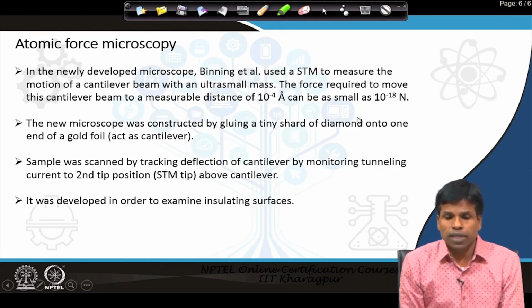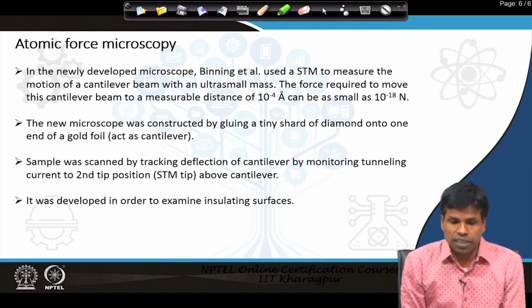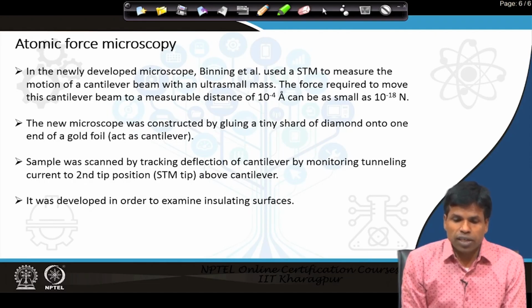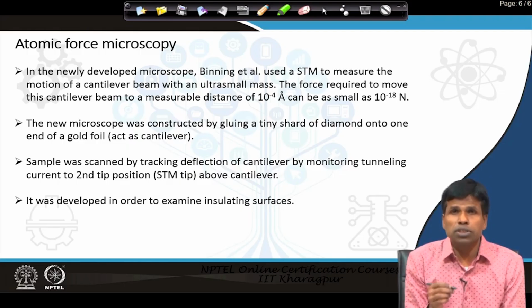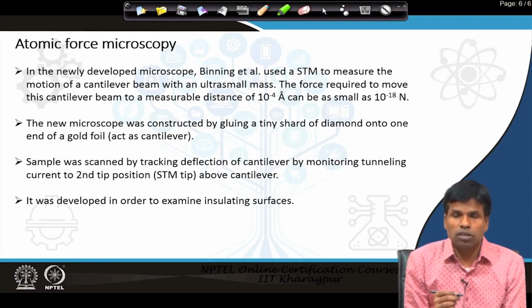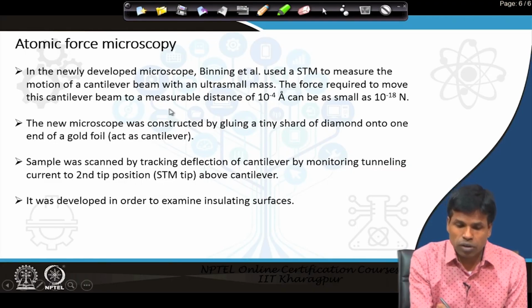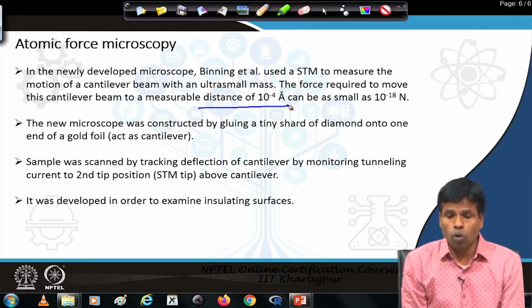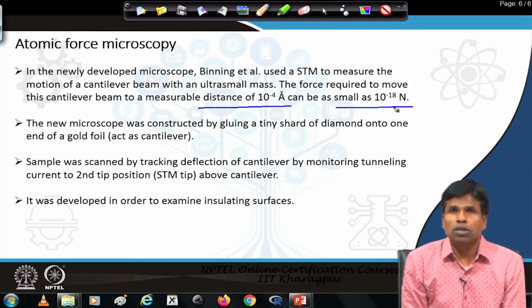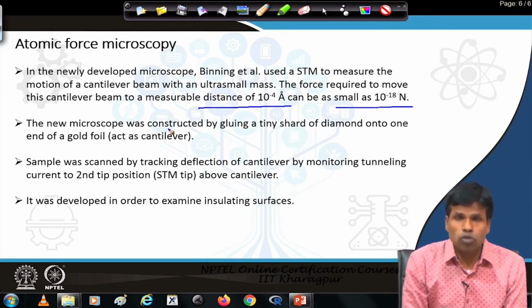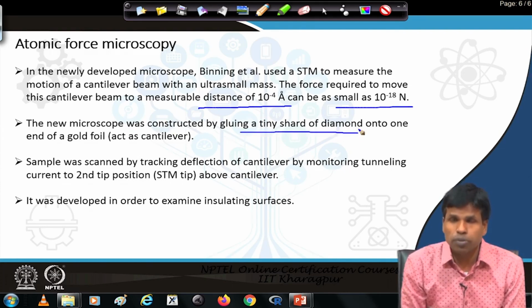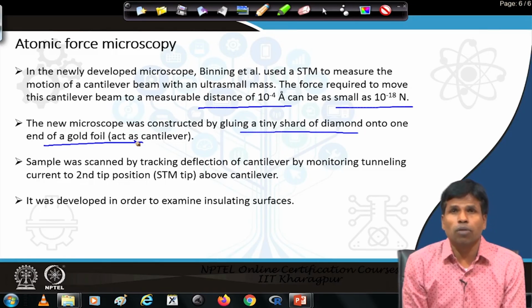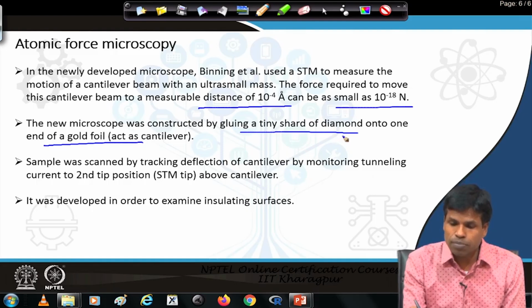So, in this newly developed microscope, they used an STM, and they used a cantilever beam with a very small mass, and using that cantilever they measured the force between the tip and sample. That cantilever beam can be displaced by a distance of 10 to the minus 4 angstrom by measuring a force of around 10 to the minus 18 Newton. This new microscope was constructed by gluing a tiny shard of diamond onto an end of a gold foil. Here the gold foil acts as a cantilever, and the tip is made of diamond.